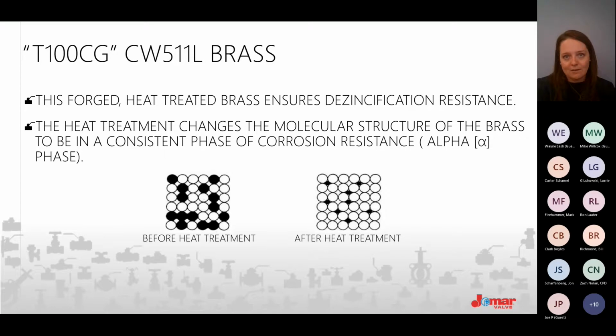We heat treat our product. So we heat treat our product to over 1,000 degrees Fahrenheit, and that changes the molecular structure of our product. It goes back to material science. Brass is composed of two phases, both an alpha phase and a beta phase. Alpha is your dezincification resistant or corrosion resistant. Beta is susceptible. So when we heat treat it, we turn it into a 99.5% alpha phase, basically making our product entirely corrosion resistant, entirely dezincification resistant, and allowing it to perform the exact same way as bronze materials in the field.